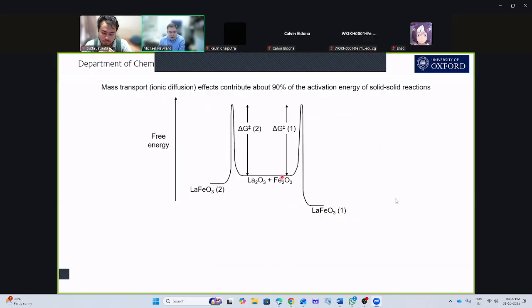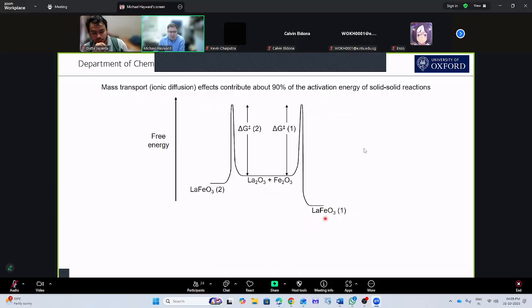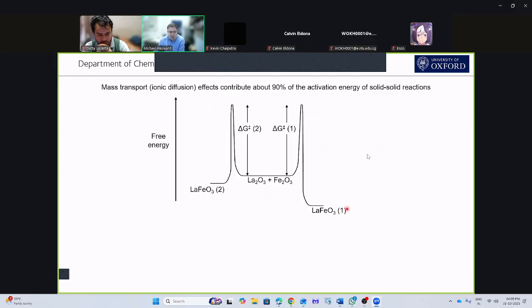And so what we could see is our starting materials have this energy here. We have lanthanum oxide and iron oxide, and we can think about them reacting to make two different forms of LaFeO3, form number 1 and form number 2. And we can see form number 1 is more thermodynamically stable than form number 2. However, what we can also see is the activation energy to form these two compounds is basically the same, because it's dominated by this large diffusion barrier contribution.